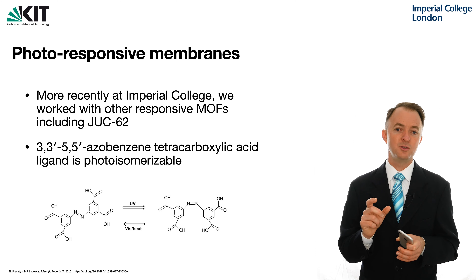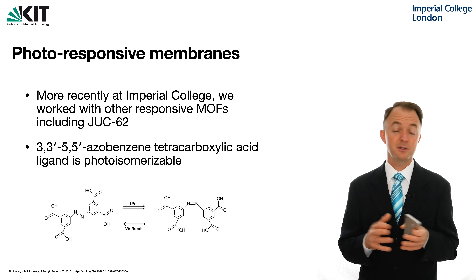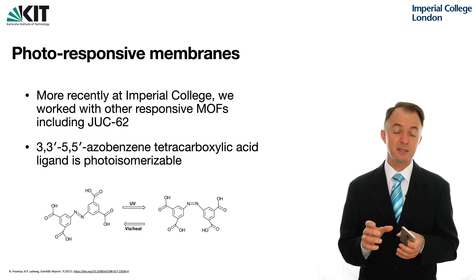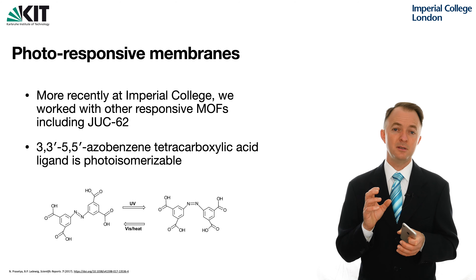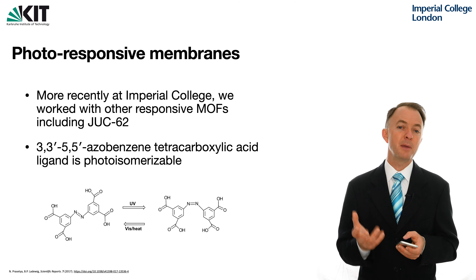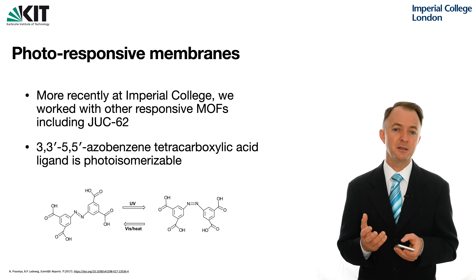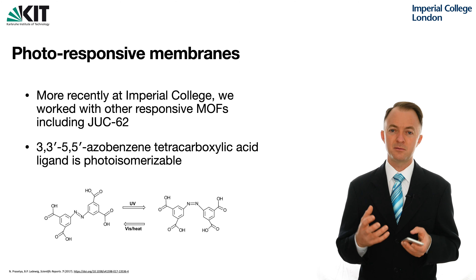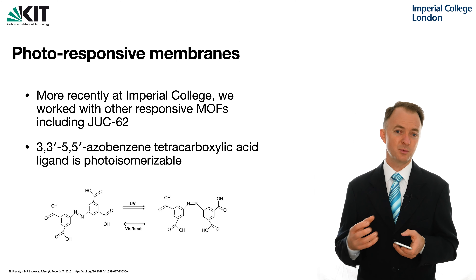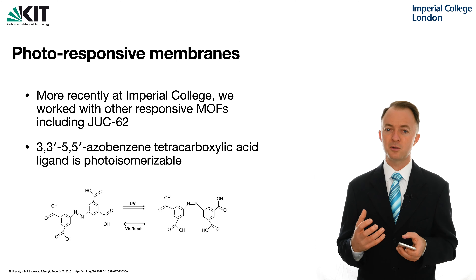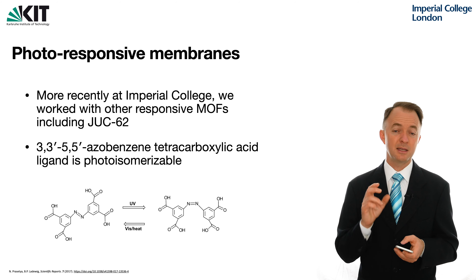This azobenzene functionality is used extensively in photoresponsive materials and especially in photoresponsive metal-organic frameworks because it's robust, relatively easy to insert into ligands, and its photoisomerisation is very well understood. We know we can photoisomerise the free ligand. When we make it into a MOF — as we showed as far back as 2013 — you can get changes to the adsorption characteristics. It's still debatable exactly how the three-dimensional porous structure changes under photoillumination because it's a constrained material and not every bond can fully photoisomerise, but it definitely changes enough that you have a substantial change in gas sorption.